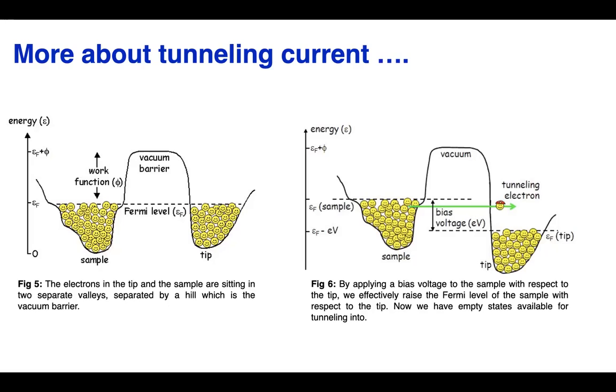To get tunneling, we have to apply some bias voltage. In figure 6, you can see that if we apply bias voltage to the sample with respect to the tip, the Fermi level shifts. When the Fermi level shifts, the electrons on the sample side see lots of empty states, so they can go and occupy those places. Then tunneling starts through the vacuum barrier. So you can see that classically it is so difficult for electrons to climb up the vacuum barrier and go to the other side.